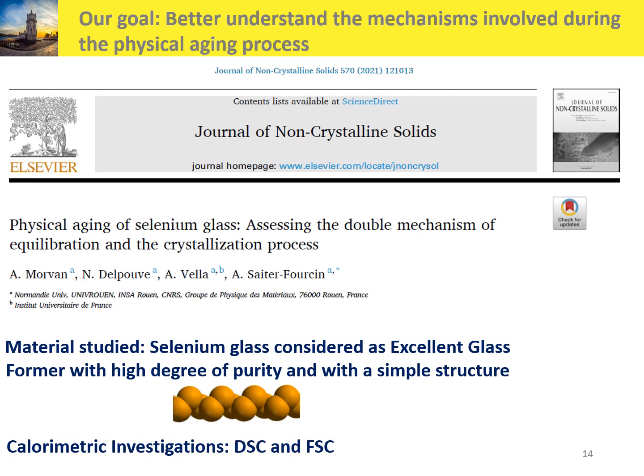So our goal was to better understand the mechanism involved during the physical aging process. To do that, we have chosen the selenium glass, considered as an excellent glass former with high degree of purity and with a very simple structure. And for this goal, we have combined two different experimental techniques, the differential scanning calorimetry and the fast scanning calorimetry.